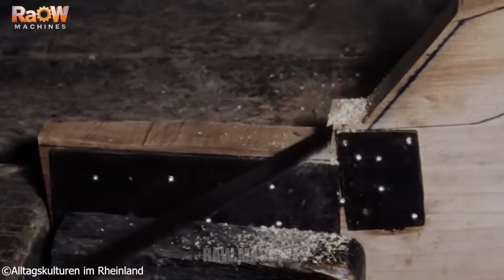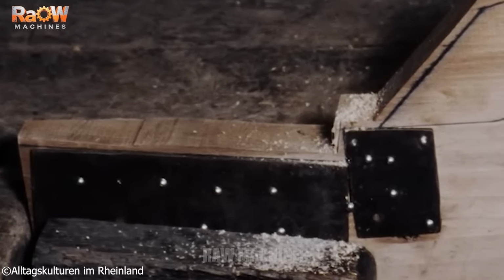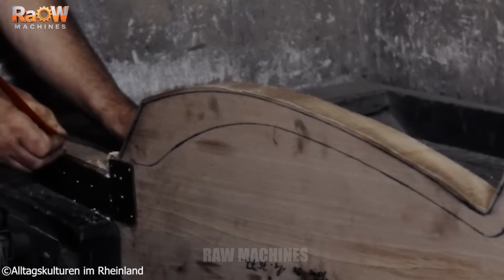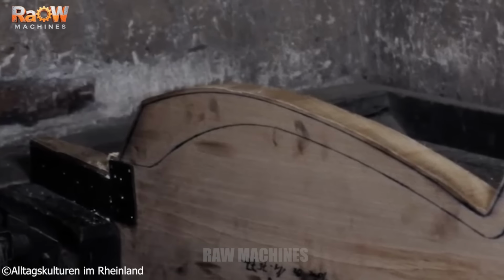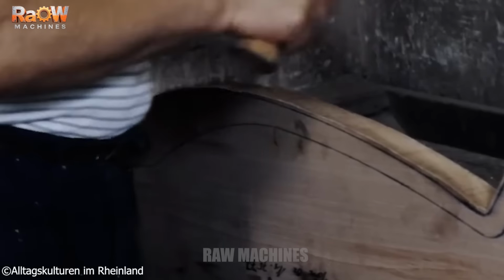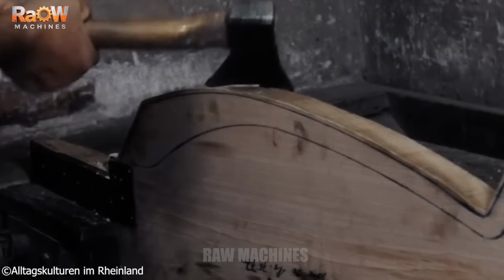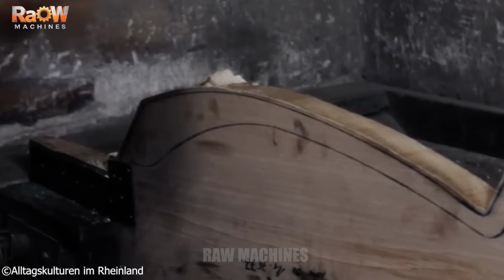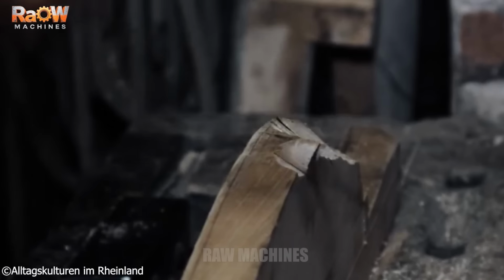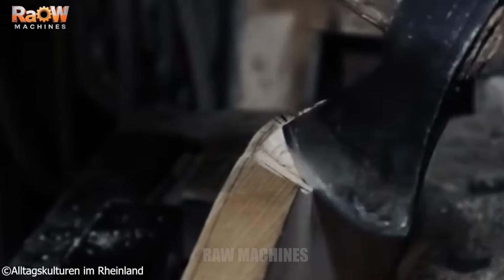The central body and the bell neck are then coated with a more fluid clay, allowing the schablone to scrape and shape the surface accurately according to the designed profile. During the initial pass, the edge of the schablone retains its full thickness. In subsequent passes, the edge is gradually chamfered inward, leaving only a very narrow contact edge to ensure geometric precision of the mold surface.